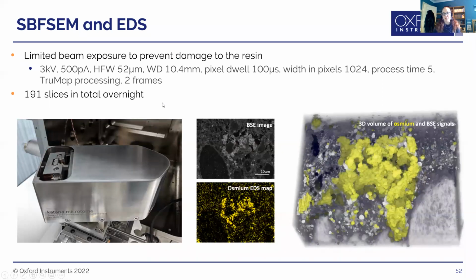Now, one of the challenges you have with any of the 3D data is the volume of your beam and sample interaction, because you've got a small slice that you're taking off the sample each time. And if you're collecting data deeper than that slice, it's going to influence each layer of data you collect. And with SBF SEM in particular, what you have is a diamond knife that slices your resin embedded sample, and you image the sample after each slice.